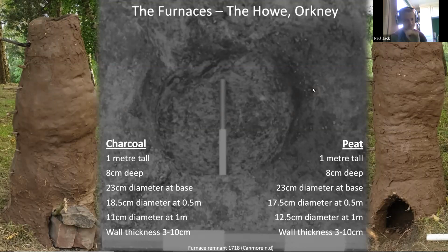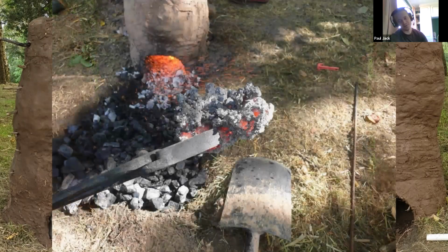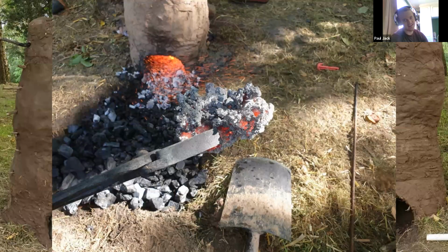We'd then fill it up with charcoal after having started a small fire, and we'd bellow our hearts away for about 4 hours or so, filling it up with charcoal and a bit of ore, and a bit of charcoal and a bit of ore, all from the top, until eventually we'd crack the front door of the furnace off, and we could extract an iron bloom, a nice spongy mass of iron and slag.